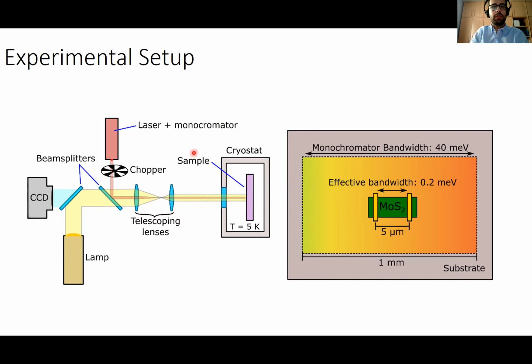And here we have the sample in this stage inside a closed cycle cryostat that is at a temperature of 5K and in vacuum. Also, we have put a lamp and a CCD camera using these two beam splitters, and this CCD camera allows us to improve the alignment between the sample and the excitation light. In this zoom, we have represented the light that goes out from the light source. Here we have the beam of the monochromator, and this beam has a bandwidth of 40 millielectron volts.